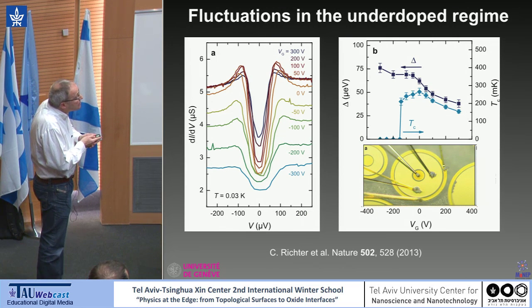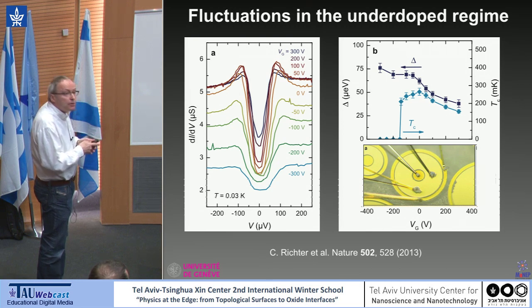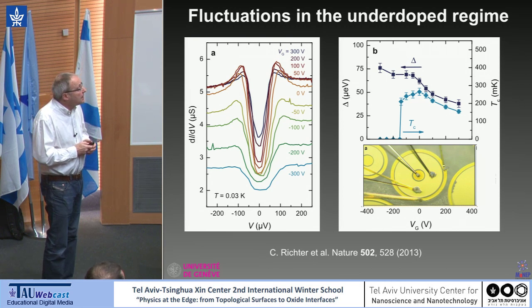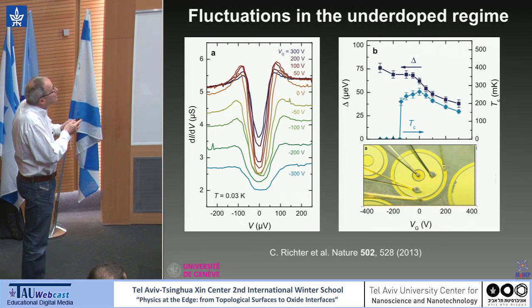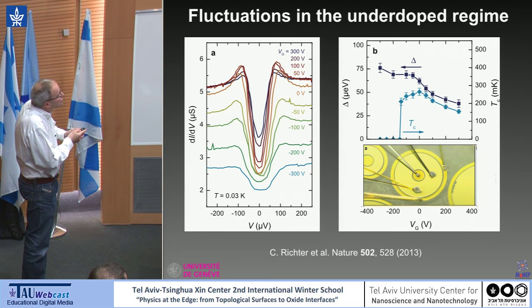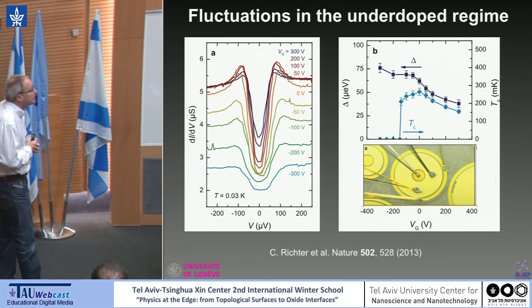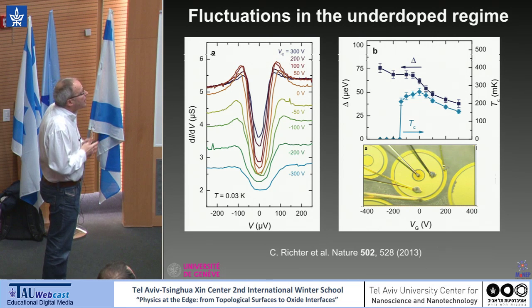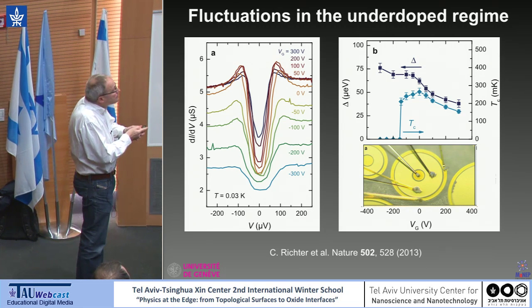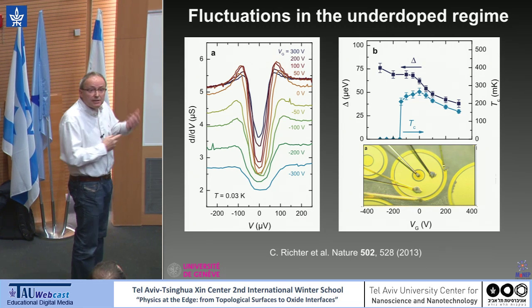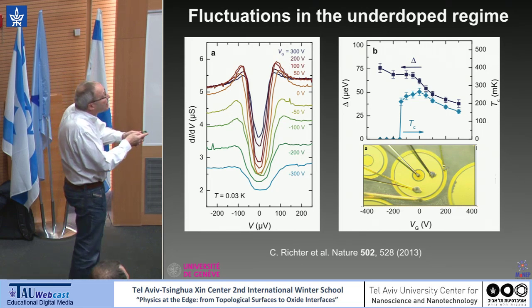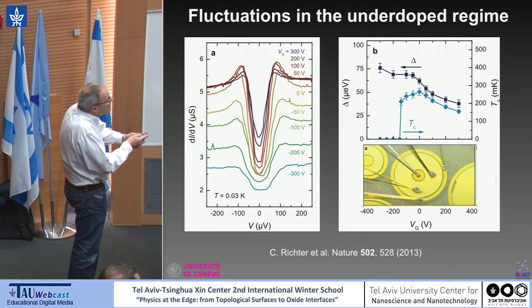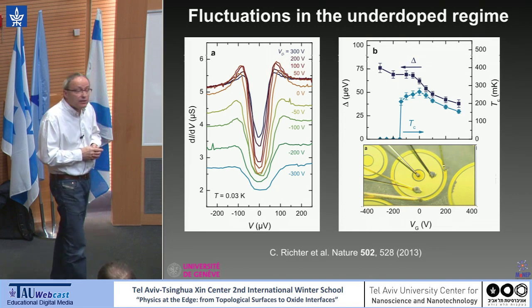So they succeeded in performing tunneling experiments through lanthanum aluminate, and they could cross the phase diagram. And you see here the conductance versus voltage from which you can extract the superconducting gap. And you can do this across the phase diagram. So this is TC. Okay, this sharp drop here is due to the definition of TC. This is essentially the dome I was talking about. And if you start from here, so this is TC and this is the gap.